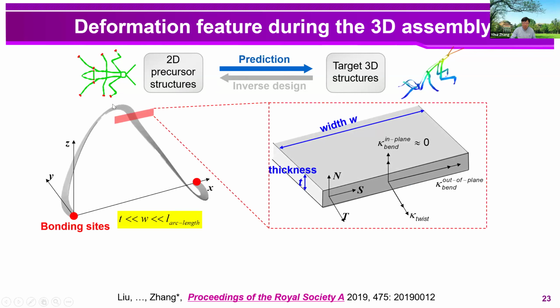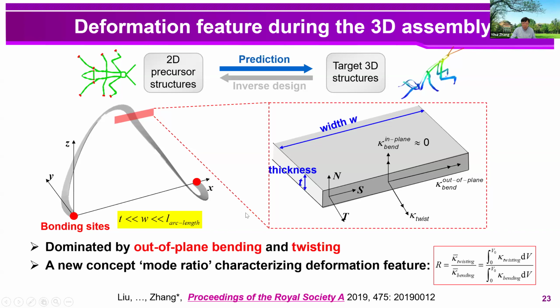And here, by using a helical 3D structure as an example, we can analyze the dominant deformations during the post-buckling process. And according to the analysis of the various deformation modes, we can determine that the post-buckling deformation is dominated by the out-of-plane bending and the twisting deformation.